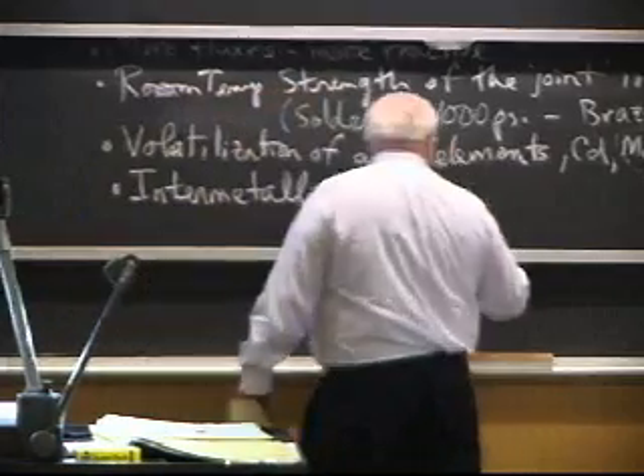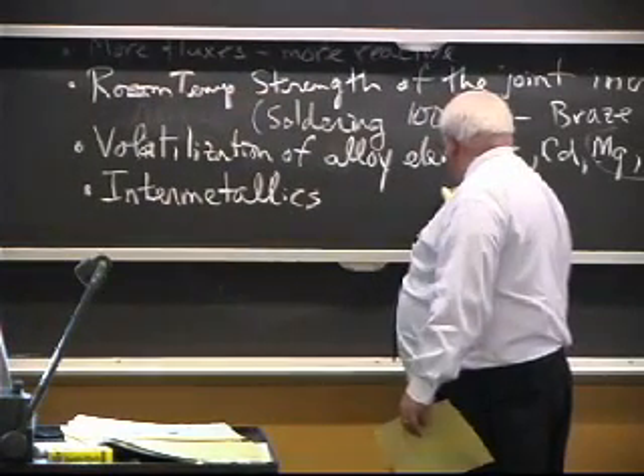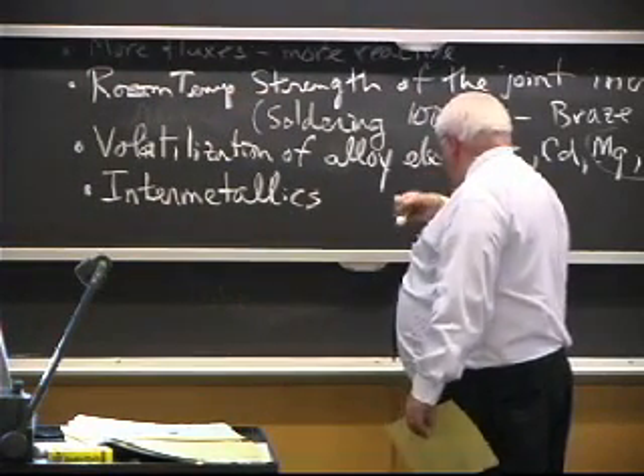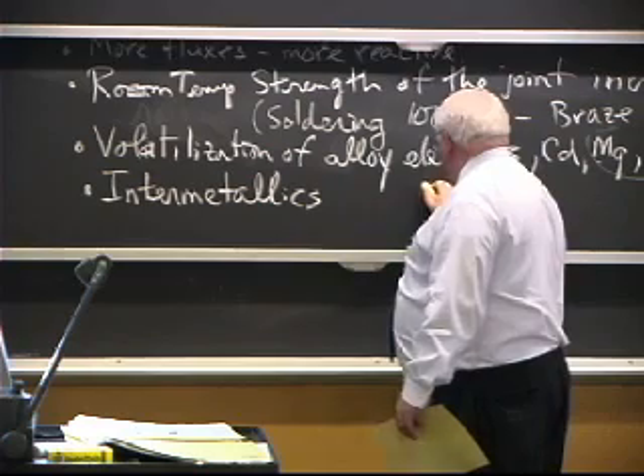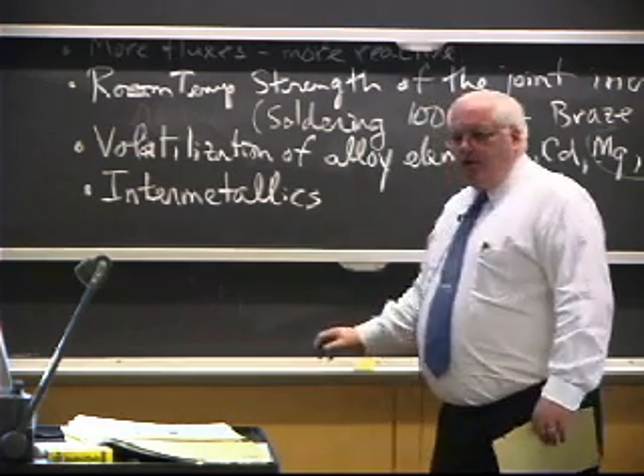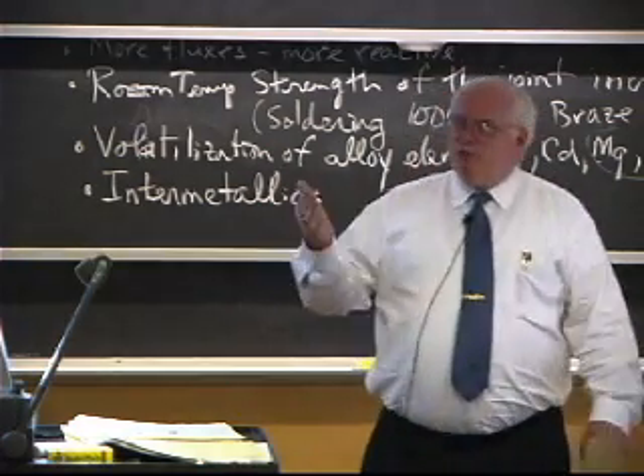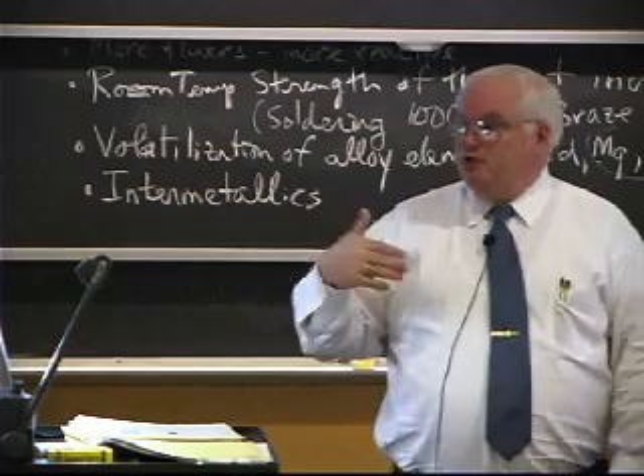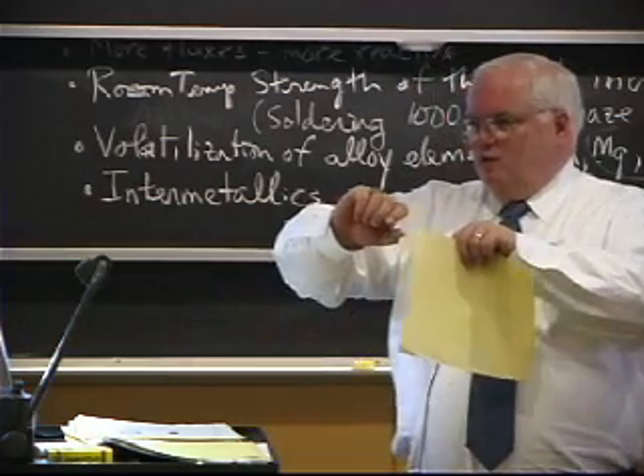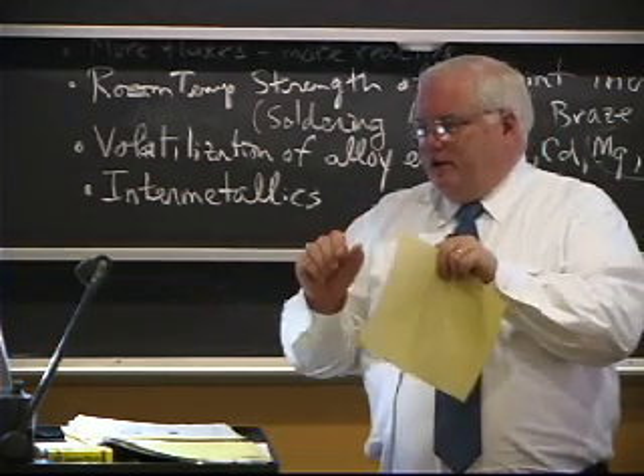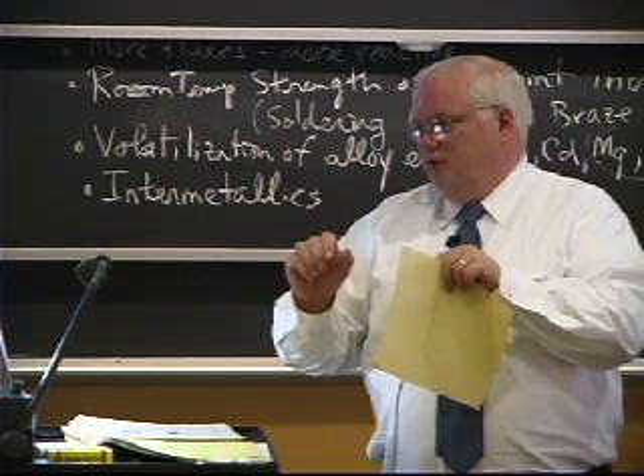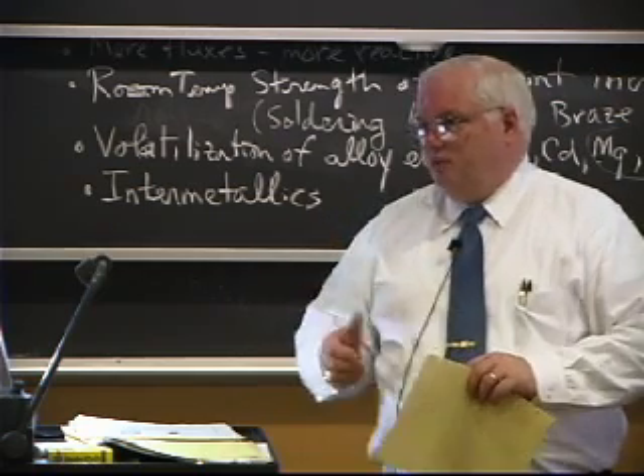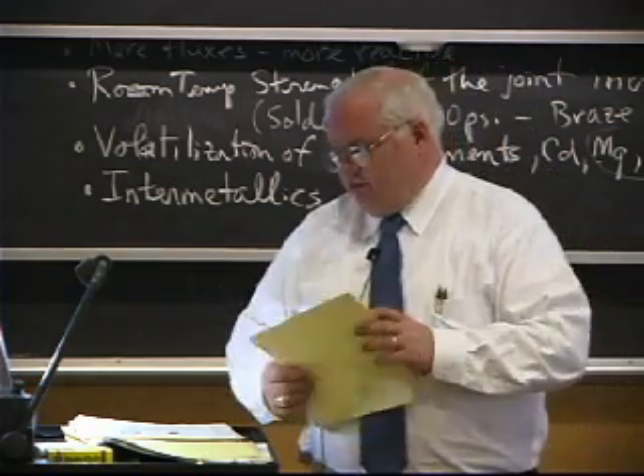And I actually gave you the example of that, the cross-field amplifier, where they were using the gold nickel braze alloy, and they were brazing molybdenum to copper, and they were getting nickel-3 molybdenum, which was a brittle intermetallic. And with that particular braze alloy, they could get like a 2-degree bend before the thing would snap in a brittle manner because of the brittle intermetallic of nickel-3 molybdenum.